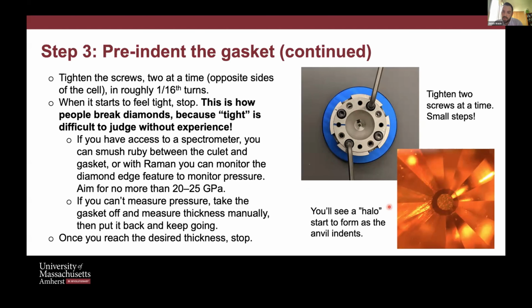And so what you'll see, again, this is hidden for me, sorry, but you'll start to see, hopefully you can see on this picture, a halo that forms around the culet. So the culet doesn't change, that's diamond, but you'll start to see a dark region appear around the side. And that's just because, if you imagine this is the anvil and we're pushing into the rhenium, because of this pavilion angle, the deeper we go, it starts to rise up the edge of that pavilion. So that, what we call a halo, is a measure really of how far into the gasket you are. So if things are going well and it feels good, it feels like you've got resistance, but it's smooth, and you're increasing the pressure, you're pushing the diamonds, you're indenting the gasket, you'll see that halo grow and grow.